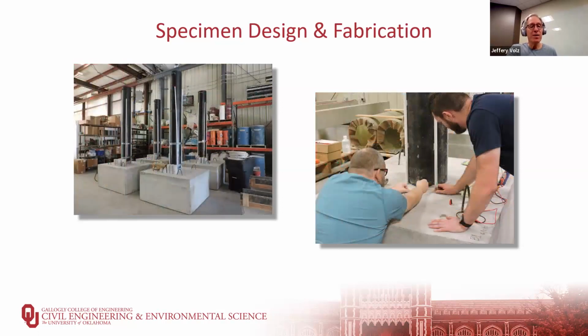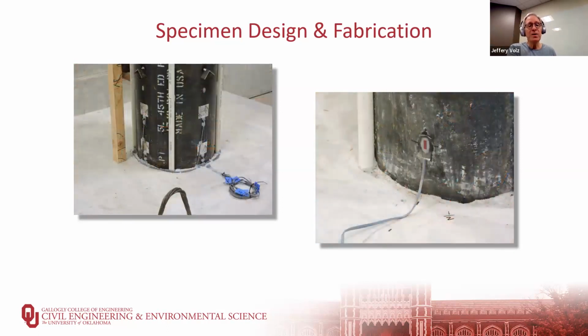On the left are 4 of the column bases with the steel tubes already in place and cured. And on the right, we are installing strain gauges on the steel tube. We installed a series of 8 strain gauges, 4 in each row at the cardinal points of the steel frame to measure strains in the longitudinal direction. The first row is at 3 inches above the column base, and the second row is at 9 inches above the column base. And you can see one of the strain gauges on the right.